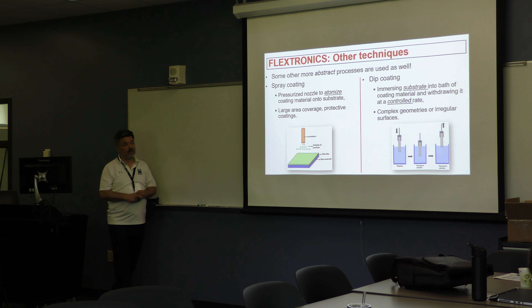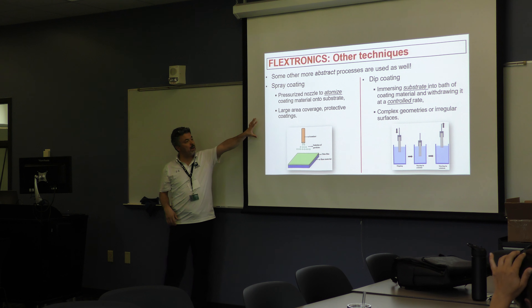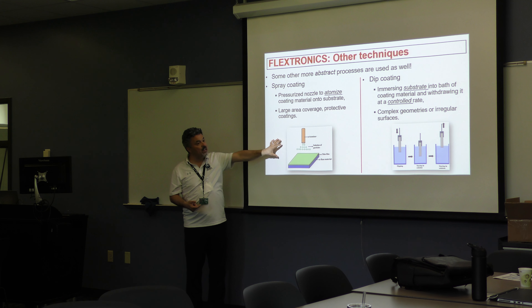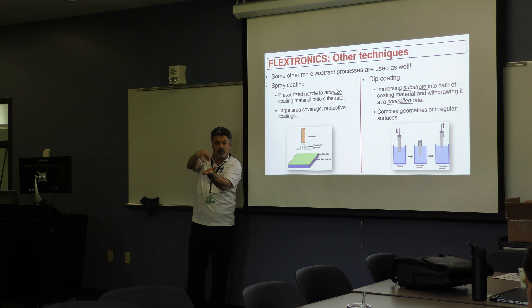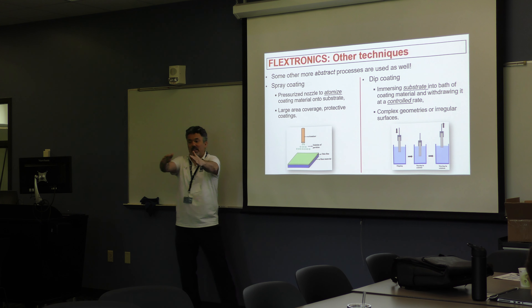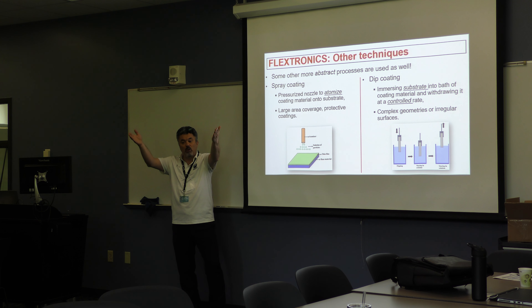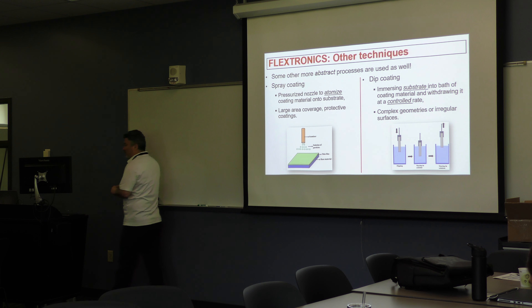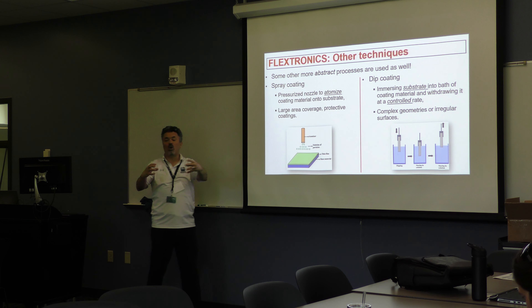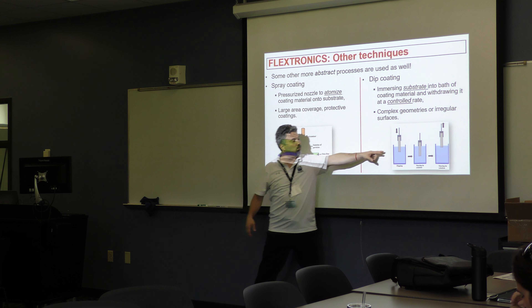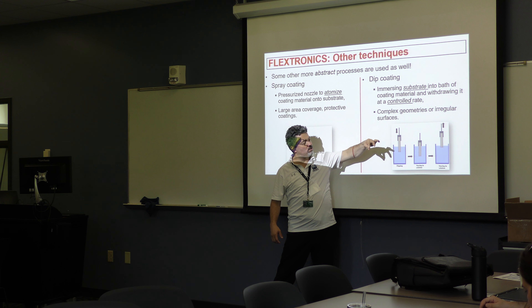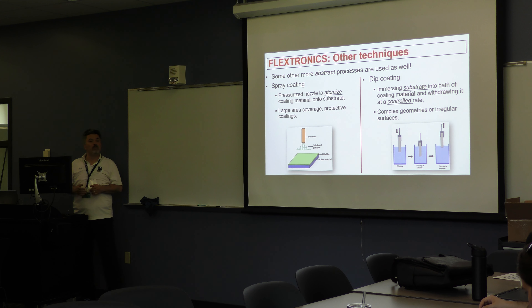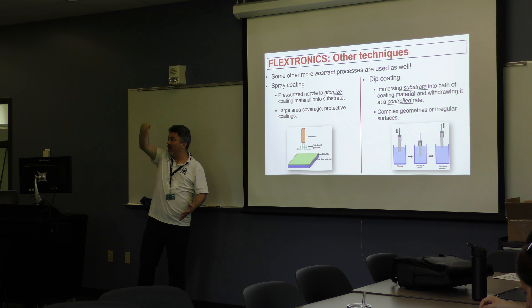For nozzle-based techniques, you could do spray coating — the quality depends on the nozzle, distance, and how forcefully you push the material. You may prefer wide spray for large area coverage, or focus it using different techniques. Dip coating is another interesting technique from surface science: assemble nanoparticles or a monolayer on a solvent surface, dip the substrate, pull it out steadily, and the nanofilm transfers onto the material — useful for large object coating very fast and over large areas.